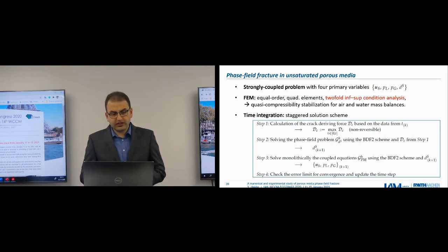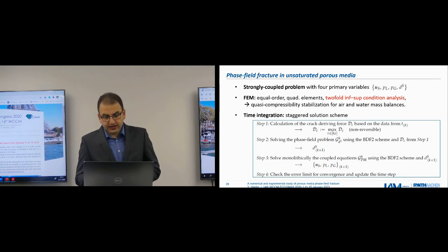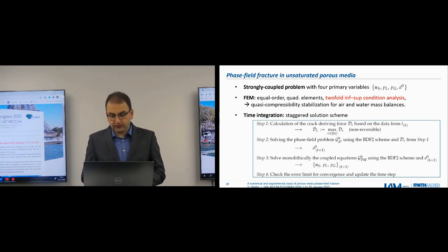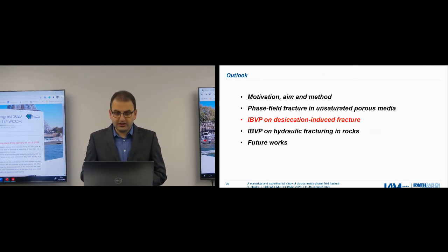In our treatment, we applied a staggered solution scheme, in which we started by computing the crack driving force, and then we solved the phase field equation in an implicit way using the second order backward difference formula. Then, when we get the phase field variable, we solve the unsaturated porous media problem in a monolithic way. And at the end, we check the convergence, and we make sure that our errors are within the limits which we assigned at the beginning of the analysis.